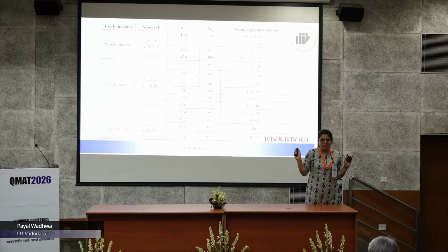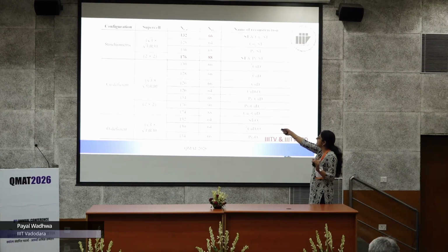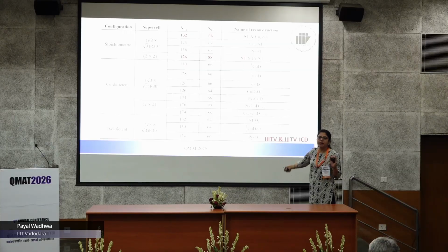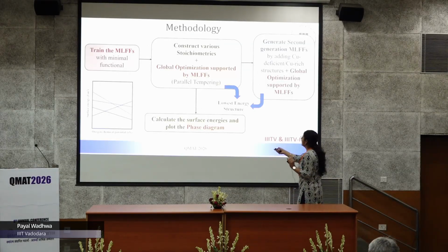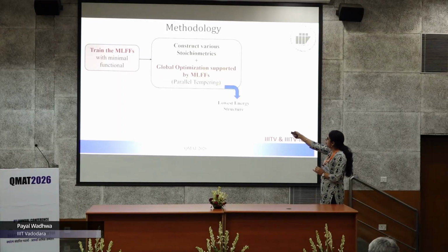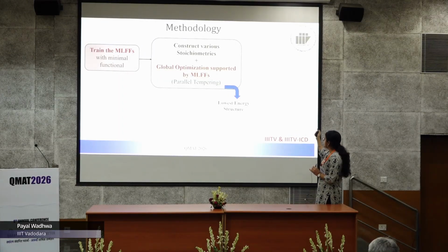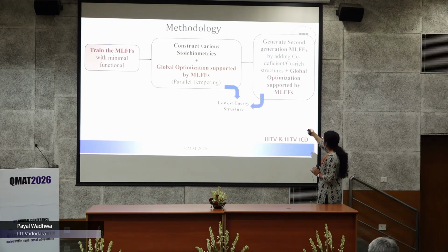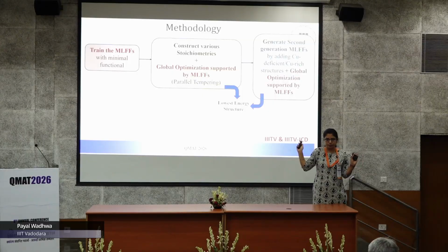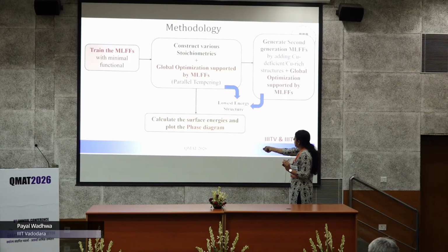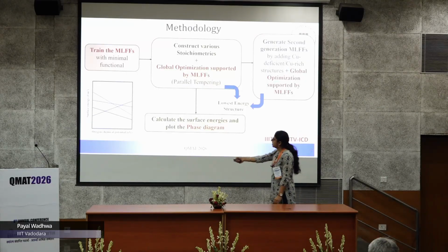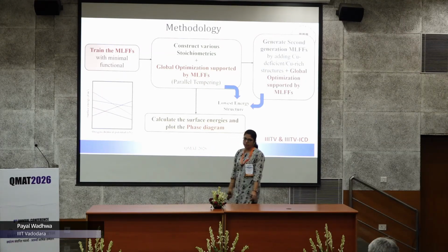Does it sound promising to you that I created the potential energy surface of this, and I am performing global optimization on some other stoichiometries? It may not. So of course, from this you can get the lowest energy structures. To overcome this issue, what we did is we added some structures from the copper deficient and copper rich states and generated second generation machine learned force fields. And from this second generation force field, we performed another global optimization, and we found that the lowest energy structures from this as well as this, there was no change in the two. And from each of these structures, we calculated their surface energy and then plotted the phase diagram. So whichever surface is having the low energy, that would be the most stable one.